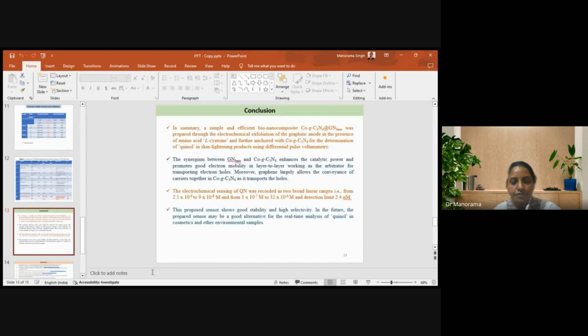A simple and efficient bio-nanocomposite was prepared through the electrochemical exfoliation of the graphite anode in the presence of the amino acid L-cysteine, and further anchored with cobalt-doped graphitic carbon nitride for the determination of quinol, which is a skin lightening agent generally used in skin creams, using differential pulse voltammetry.